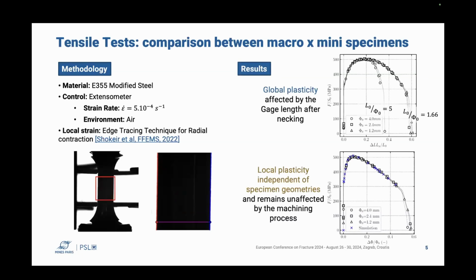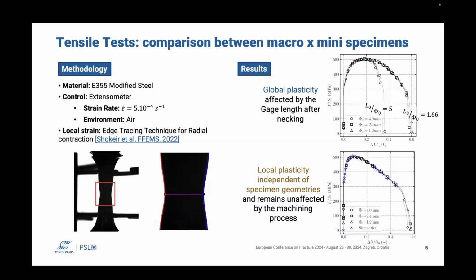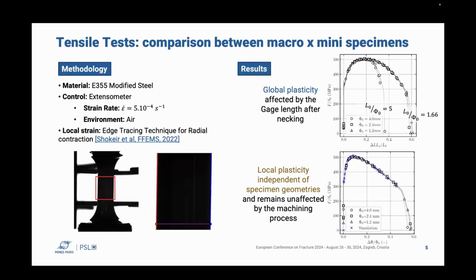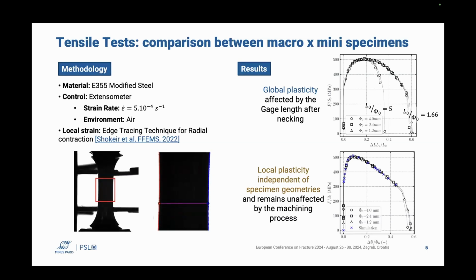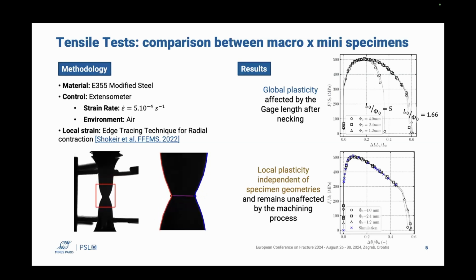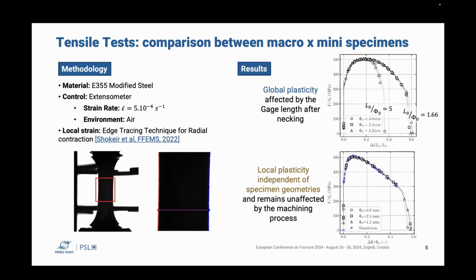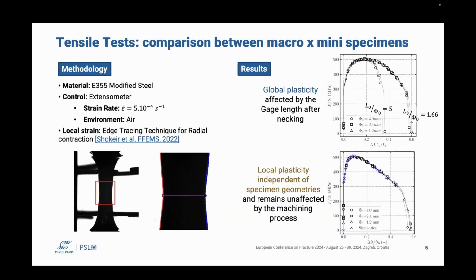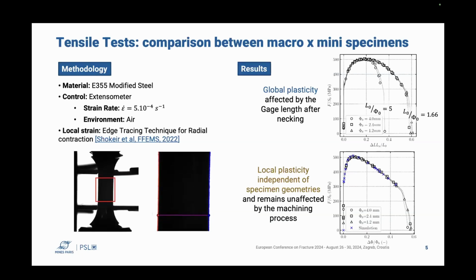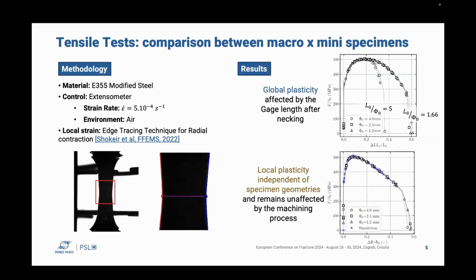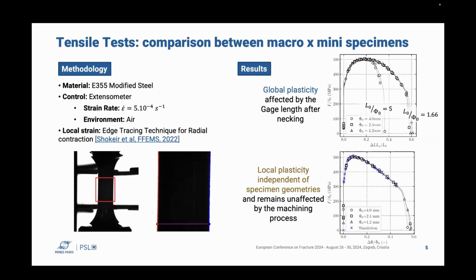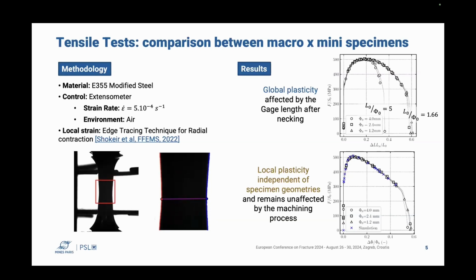The results show that the global plasticity is affected by the geometry of the specimen. We can see here that the two mini specimens are here, and the standard one is here. So we can assume that the ductility is increased for the mini specimens. But when we look at the local plasticity, we can see that it is independent of the specimen geometry. Here we have the stress plotted against the radial strain. We can see that they are equivalent, it doesn't matter if it is a standard specimen or a mini specimen, and it is not affected by the machining process either. That was a concern.